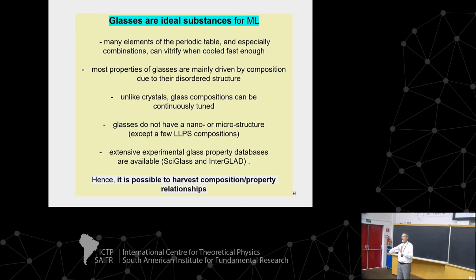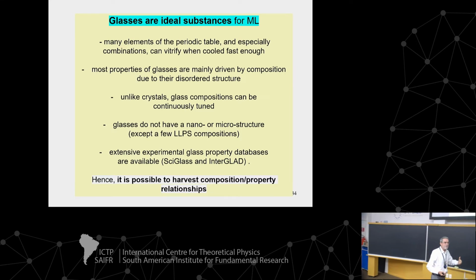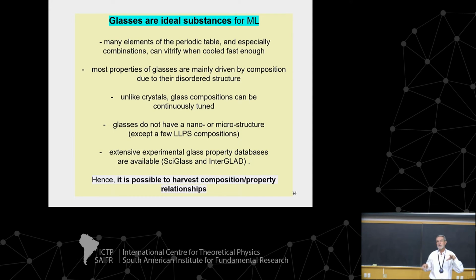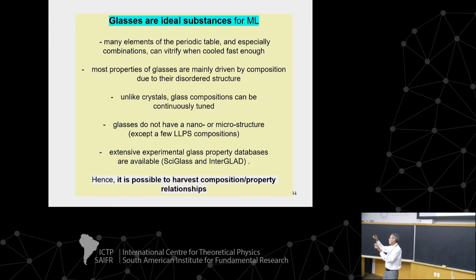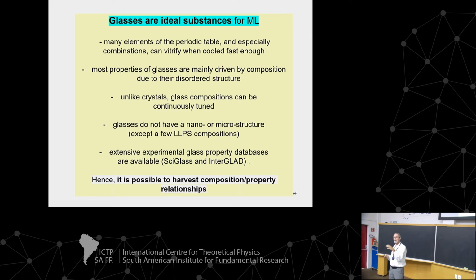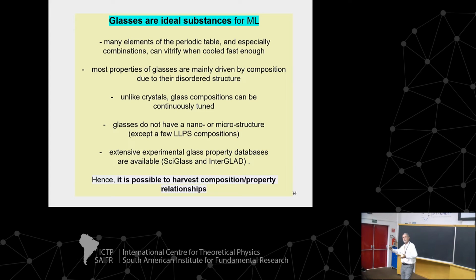We can train different algorithms by inputting data. People have measured 1 million glasses. If I can have some students collect all this information from the literature, the chemical composition with the refractive index, the hardness, the thermal expansion coefficient, the density, the specific heat, or any property, you feed this information to some machine learning algorithm. There are many algorithms. The algorithms themselves generate empirical models. This is brute force statistics. They generate models to correlate compositions and properties. That's the idea.